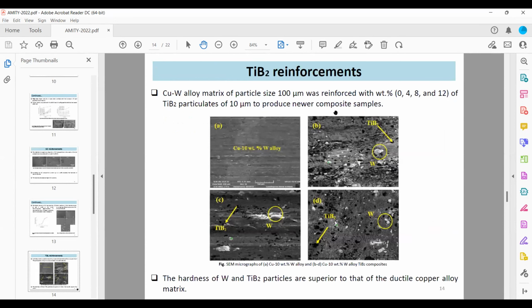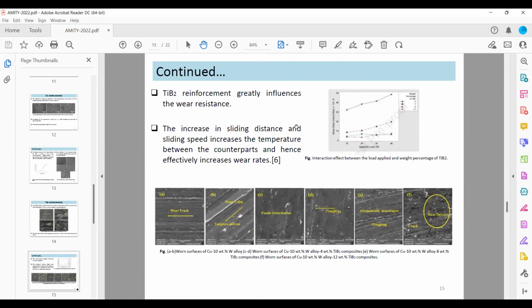TiB2 reinforcement. TiB2 is usually used along with a copper tungsten alloy matrix, because TiB2 provides thermodynamic stability, and there is a homogeneous dispersion of tungsten carbide. But when TiB2 is added, it reduces the mobility of the grain boundary and it obstructs the dislocation motion, thereby cluster formation decreases in the microstructure.